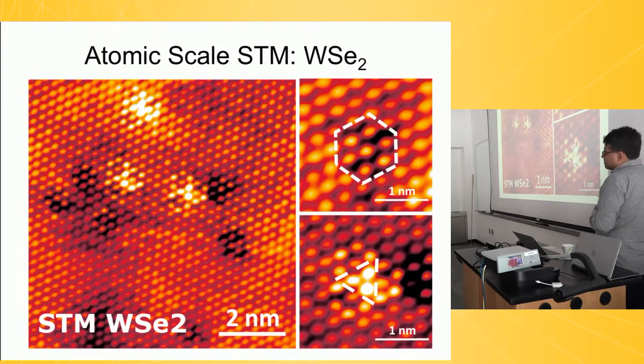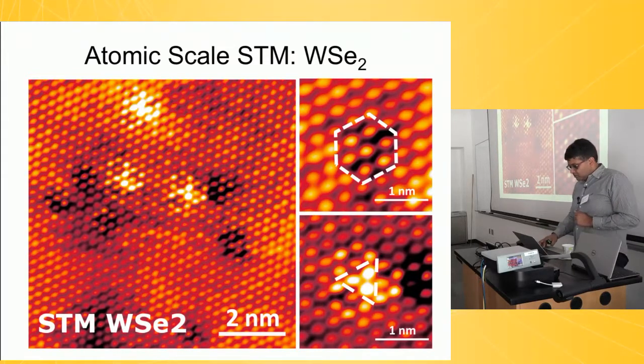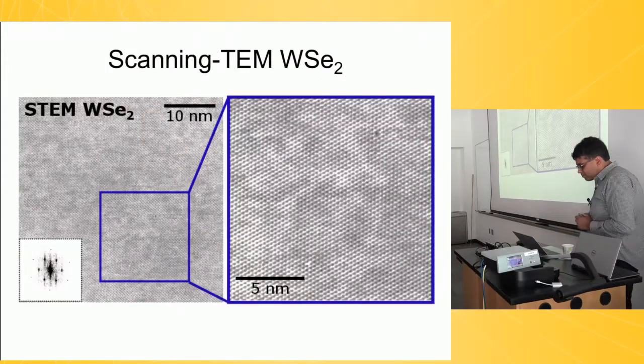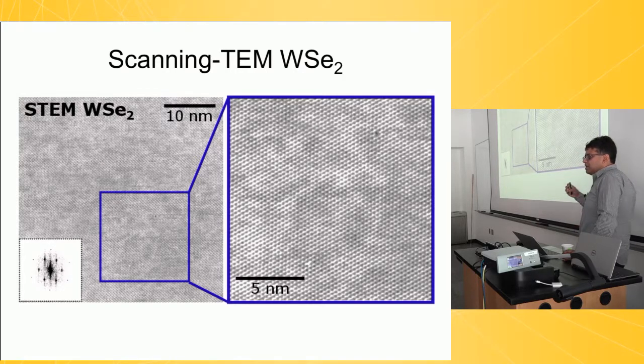We've done the same thing for WSe2. And once again, we see the same two defect types. Same story as before. Now, as far as the metal vacancy goes, we can take this material, exfoliate a single layer, put it in a TEM, and just look for metal vacancies. Metal vacancies are not all that difficult to see in a good TEM these days.